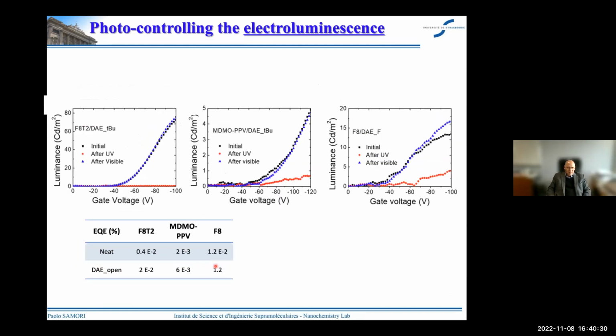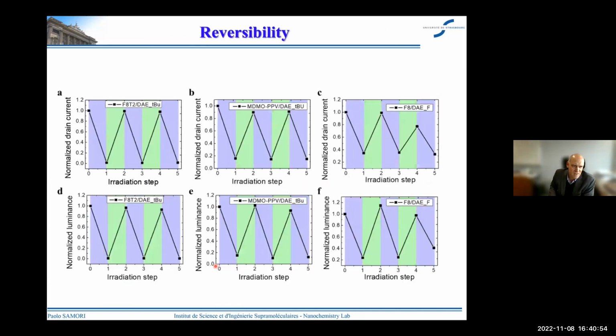We can do this very same game by looking at the luminescence. So you can see that we have a luminescence that is quenched completely when we bring the diarylethene into the closed state, whereas when it is in the open state, the system is still luminescent. And so here we can have again an on-off ratio of the luminescence that exceeds 500. So we can make cycles with radiation, with UV and visible light, to trigger the isomerization from open to closed state. When you're in the closed state, you trap charges and you quench luminescence. And you can see that we can do this for all the three types of blends, and therefore for the emission of light at different colors.